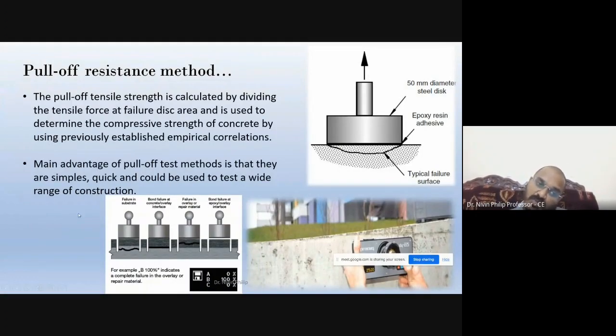One thing you should remember: after fixing this disc, we have to isolate this portion by making a circular cut, a 50 mm circular cut, up to the reinforcement layer. Then you place the disc. Otherwise, when we try to pull out, the nearby cover concrete will also influence the bonding and show some effect on the bond strength. So we have to isolate the glued portion from the remaining concrete. That's why you can see a cut made in this area.